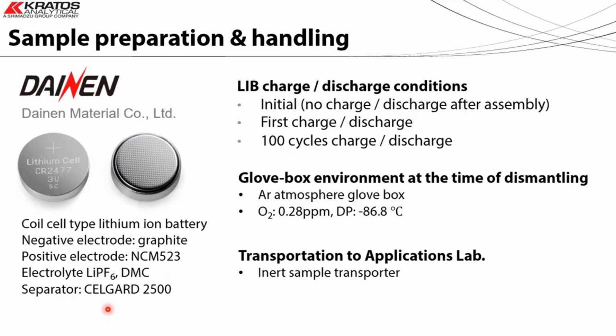So we essentially had access to 3 samples. The first was as manufactured, so it's undergone no charge or discharge, so it's freshly assembled. A sample that has undergone 1 cycle, and then another sample that has undergone 100 charge-discharge cycles.